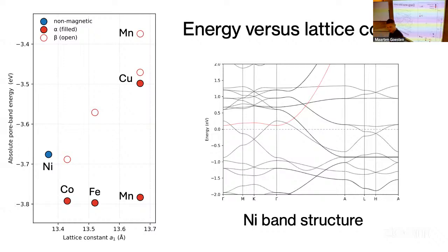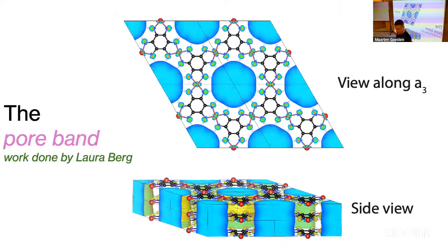No, so if you look at what happens when you go from, so what you see here essentially is that the band is very flat. So you should think of this as just an electron, okay? And it's in this pore, so it's actually kind of tubular. You can see it's like a worm. So what you see is that in the gamma M K gamma direction, you get very flat dispersion. That's because this electron and these electrons, they barely feel each other in this direction. But if you go from gamma to A, what you're doing is you move from a system without node.